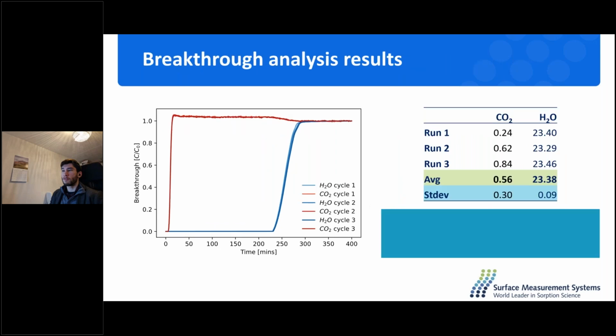And here are the results of the integrations of these two curves to obtain the uptakes of each component. This is in weight percent. On average, we have around 0.5 weight percent CO2 and 23.4 weight percent water at these levels. If we remember the isotherms that were recorded from DVS, at 3.5% volume CO2, we would get about 7.6% by weight CO2 uptake.